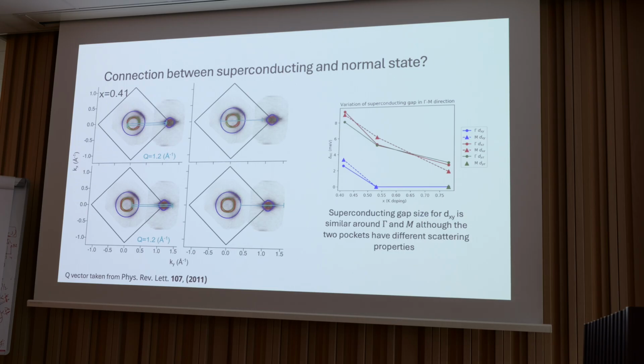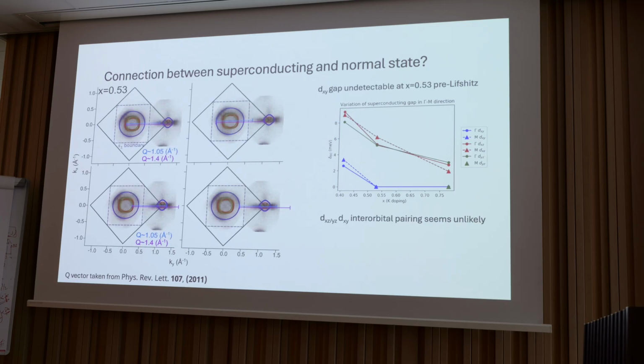So what we see is that the superconducting gap size for DXY, if you remember, is very similar around gamma and M, although the two pockets have very different scattering properties. So we can maybe try to rule out any type of interorbital pairing, but maybe we can ask why we see this gap on the DXY band at all. Maybe there's some interorbital pair hopping. I don't know, maybe the theorists can comment on that more. But I just want to make a point. And then for 53%,